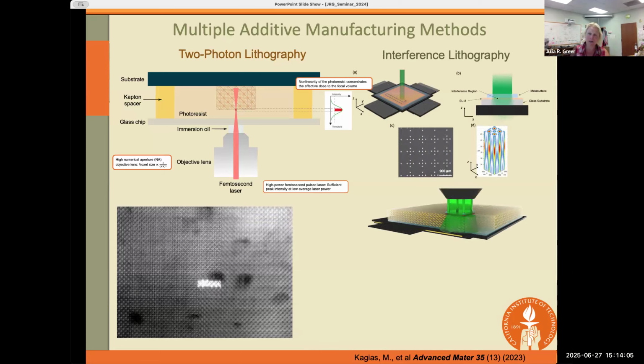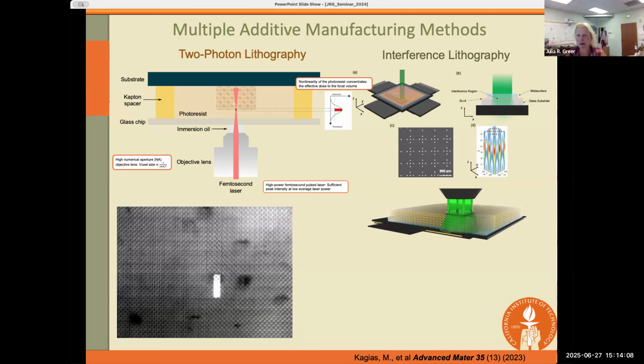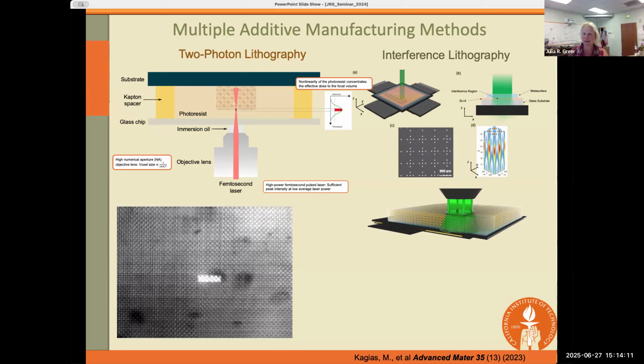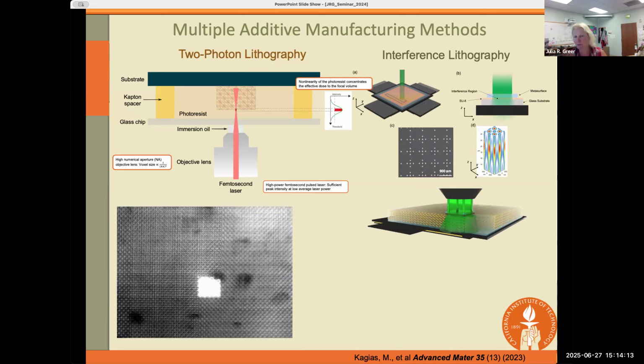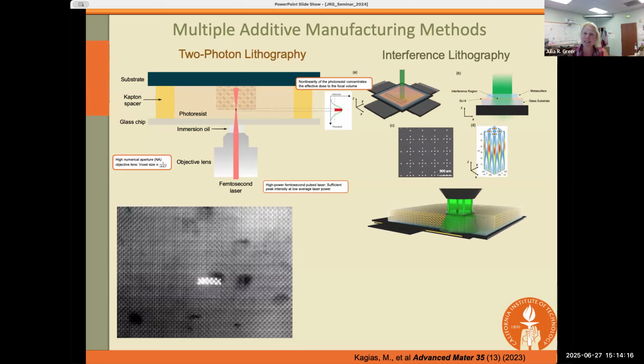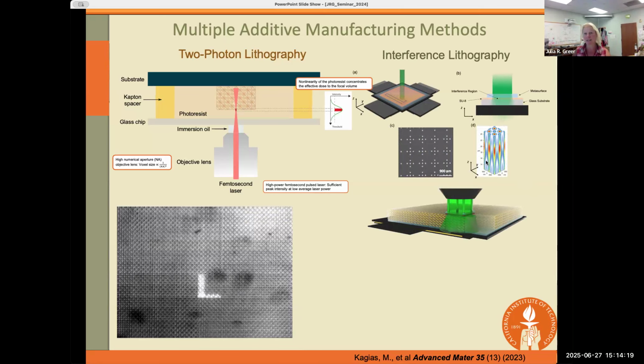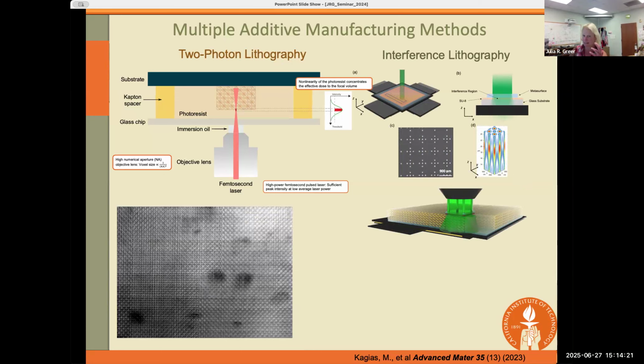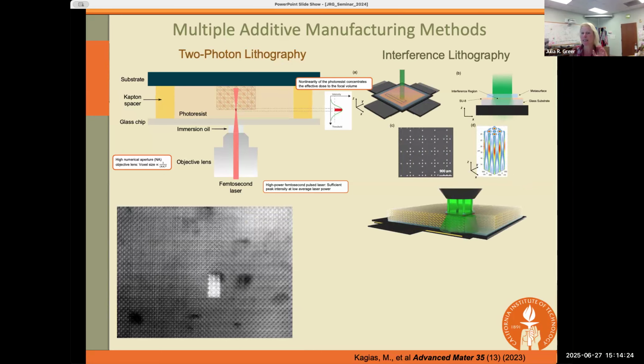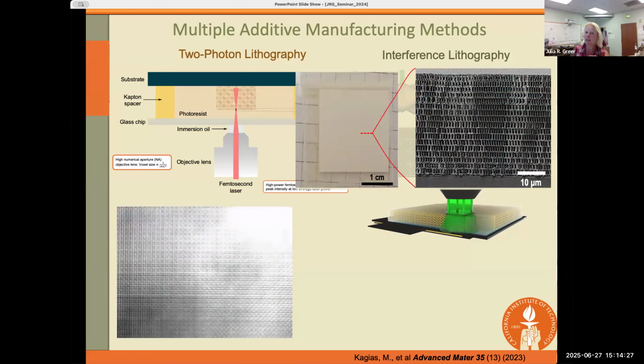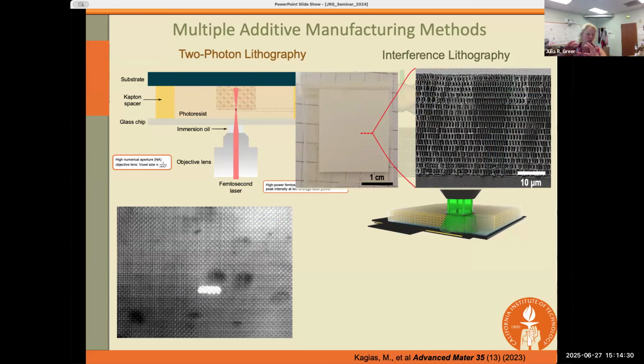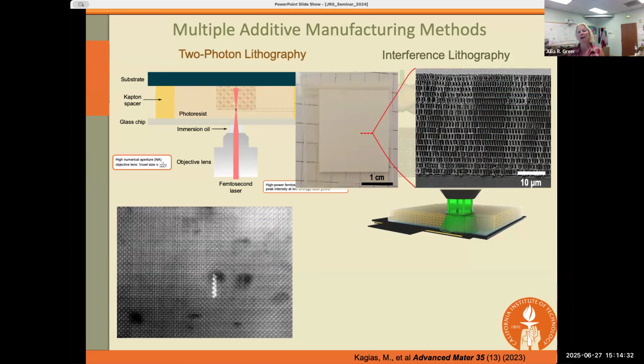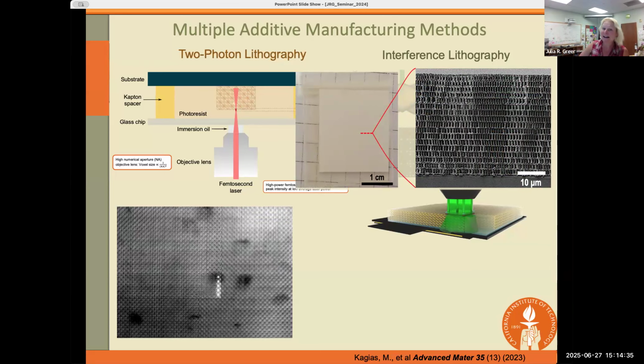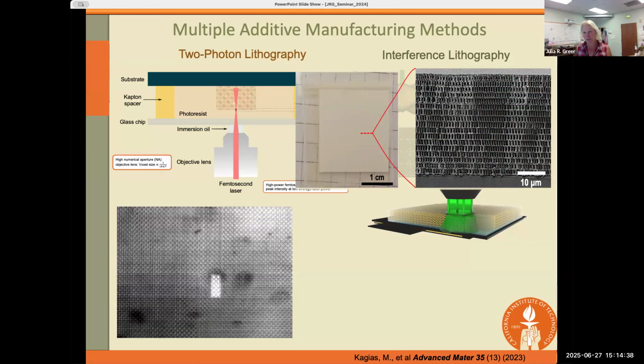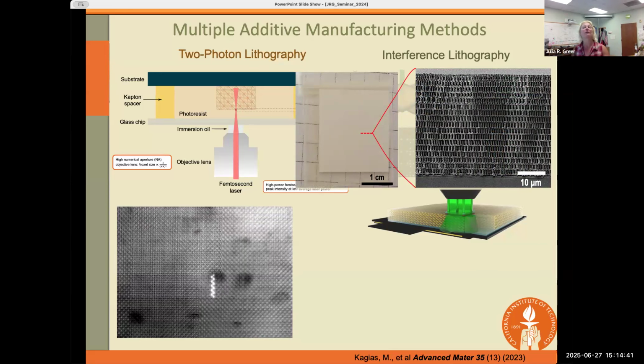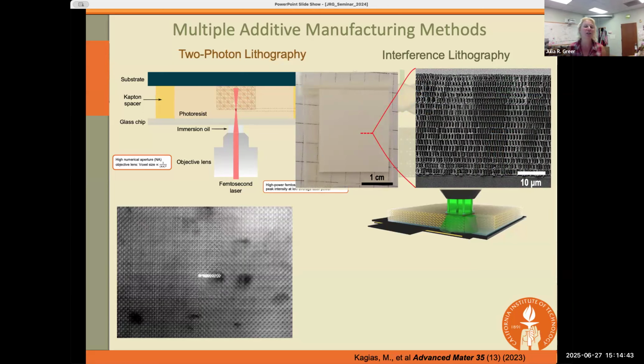So this is a collaboration with my colleague Andre Faraon, who works on metasurface masks. And the idea is that it creates a 3D interference pattern with light. And now these points of high intensity that you see here can be translated into a photosensitive resin and then cross-link the polymer in a similar fashion as the 2-photon lithography, but in a single laser exposure. And the advantage of that is that we can now make effectively sheets of paper. So what you're looking at here is effectively a centimeter by a centimeter sheet, which in our world is very big. And when you create a cross section of it, you can see it's fully nano-architected all throughout its thickness with a pitch of about 500 nanometers.